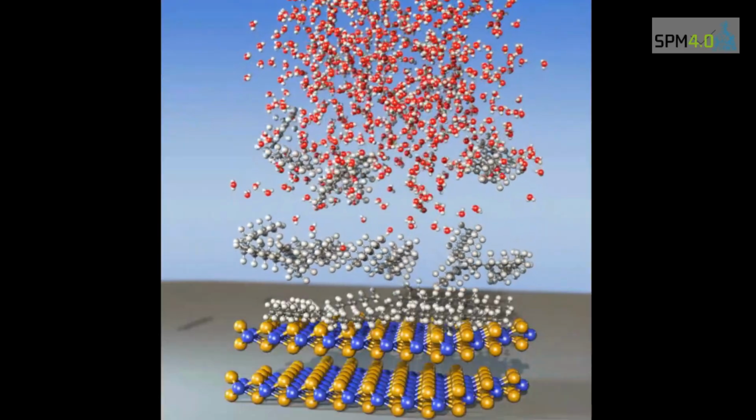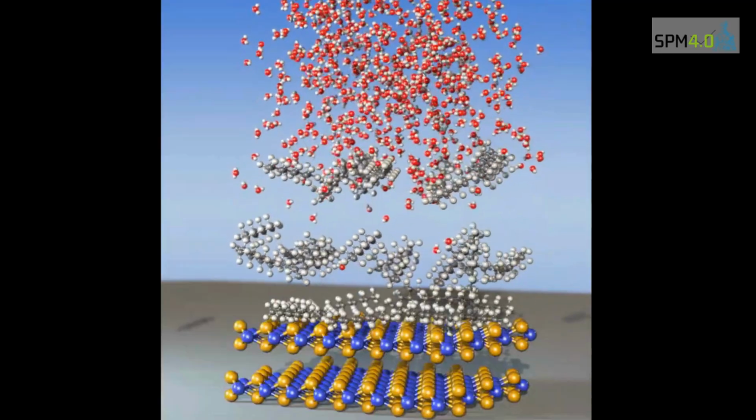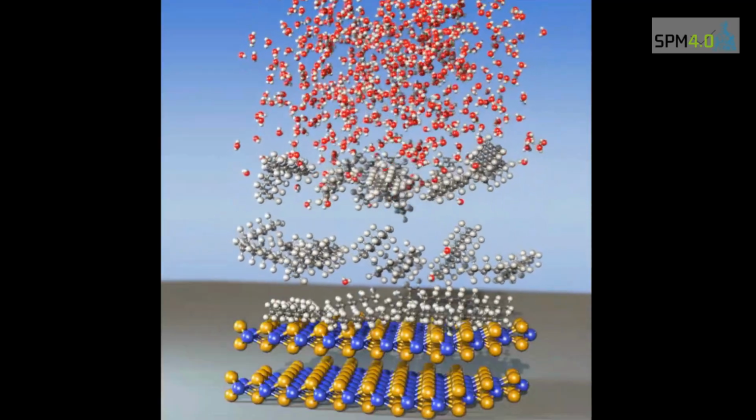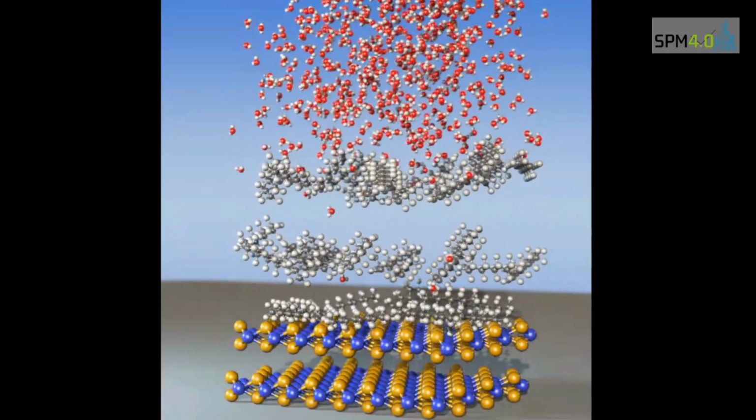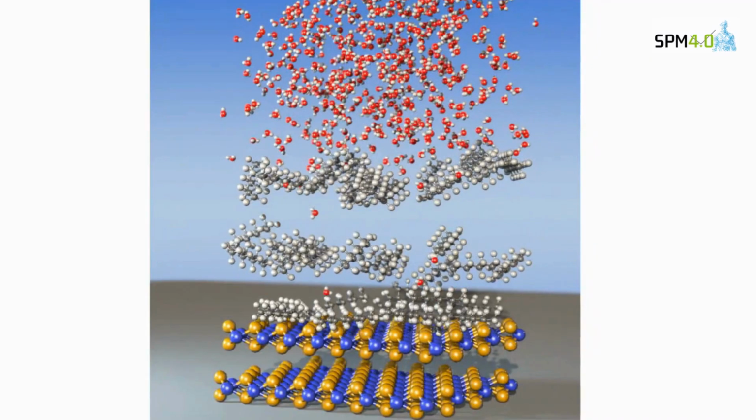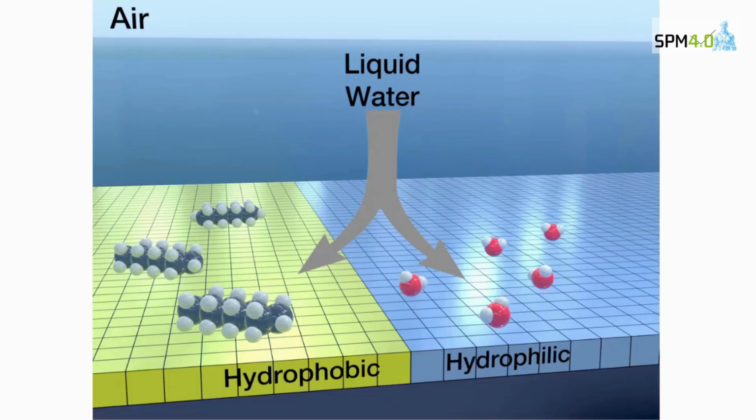Of course, if you do this experiment with a hydrophilic surface in the water, there are also these hydrocarbons. But what happens is that when the hydrocarbons diffuse and go to the hydrophilic surface, the mica doesn't like the hydrocarbon. So the hydrocarbon goes there and moves away. And the water molecules stay there because the mica likes the interaction more. This likeness is expressed in terms of free energies. So that's the conclusion, that the water structure is different on a hydrophilic surface than on a hydrophobic surface.